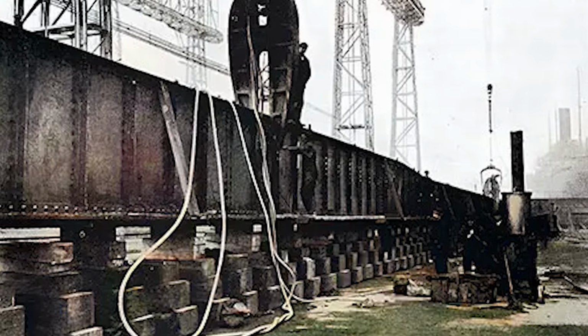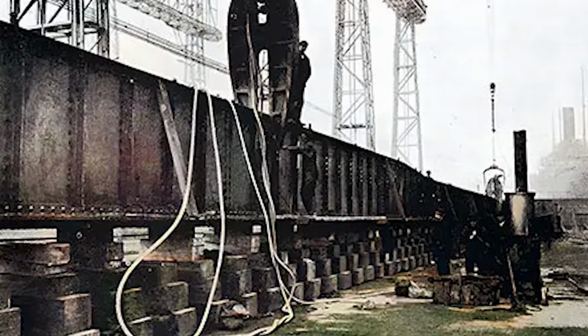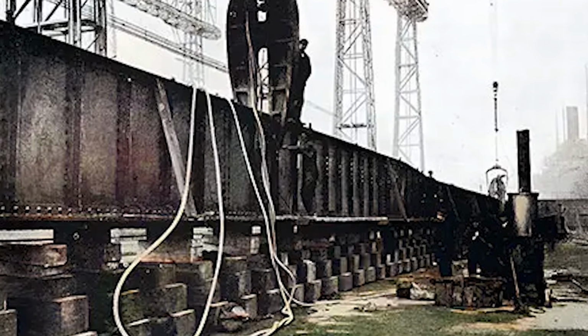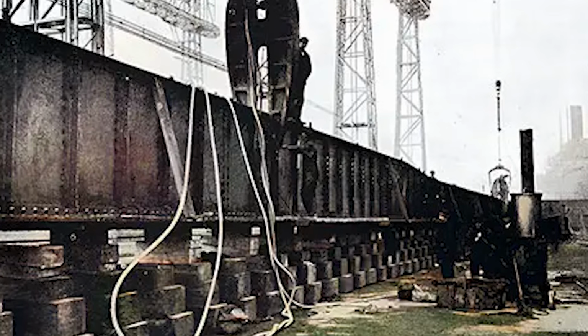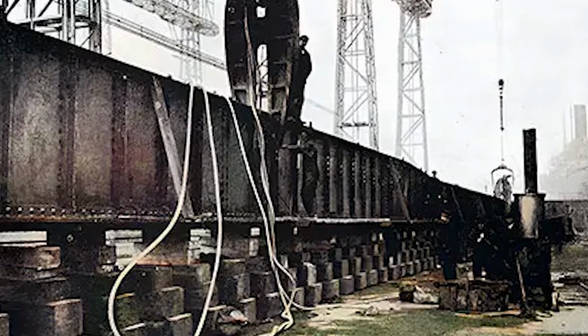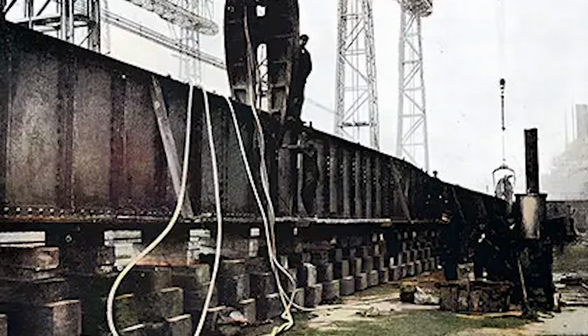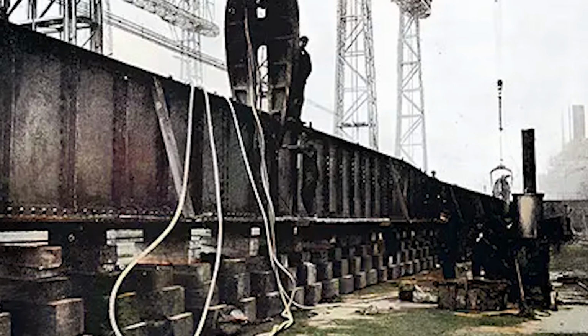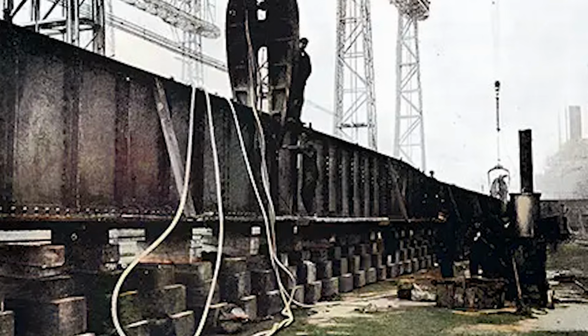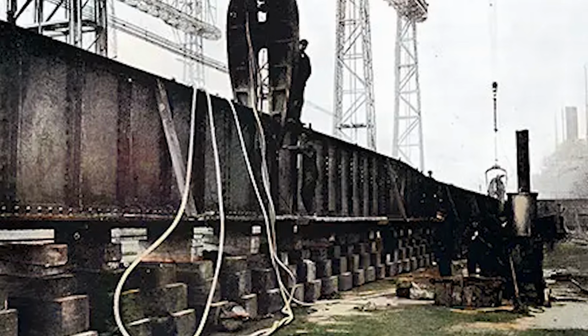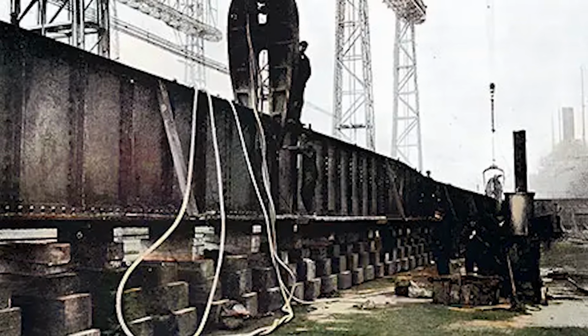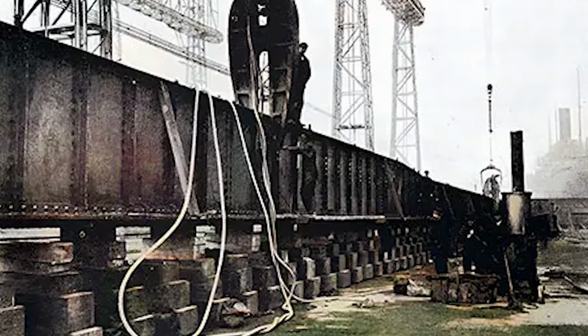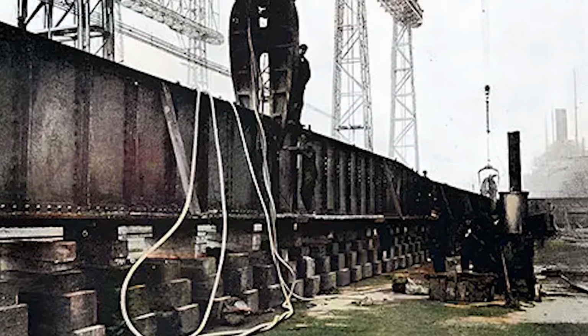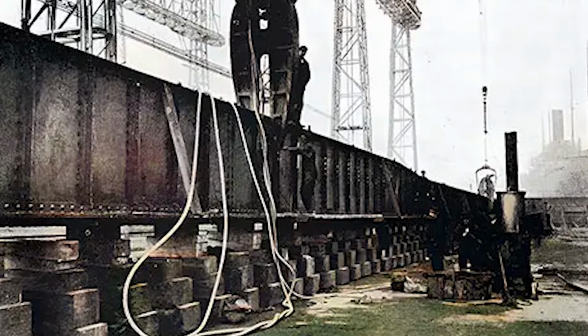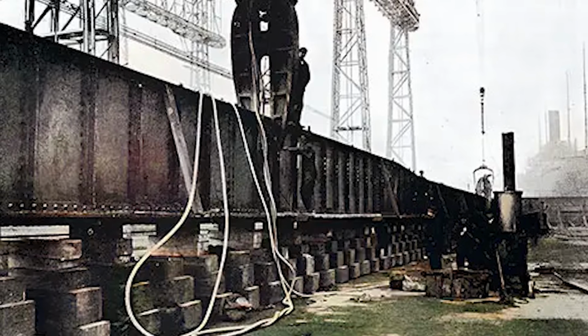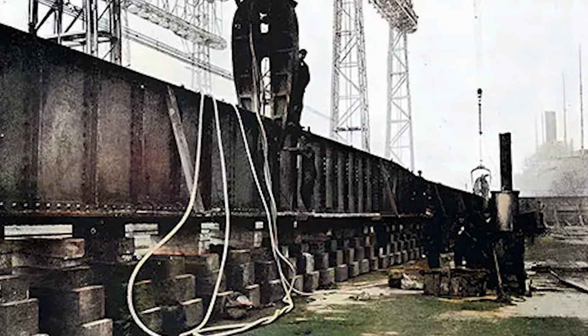William Francis Gibbs testified with grim satisfaction that vindicated his earlier warnings about untested welding techniques. Traditional riveted construction had never experienced comparable catastrophic failures because overlapping steel plates provided natural crack arresters that prevented fractures from propagating across entire hull sections. Riveted joints allowed controlled flexibility that absorbed wave energy through thousands of individual connection points, while welded construction created monolithic structures vulnerable to complete failure if cracks initiated anywhere in the hull.